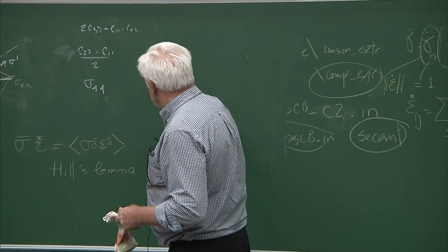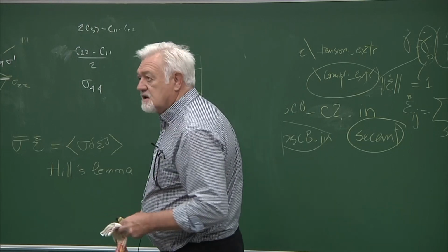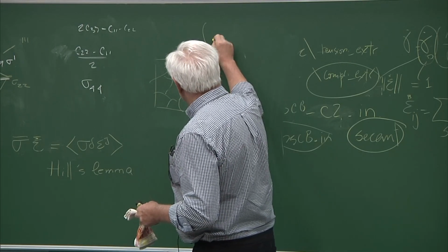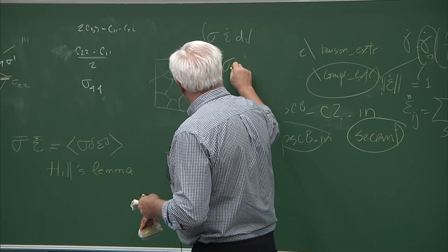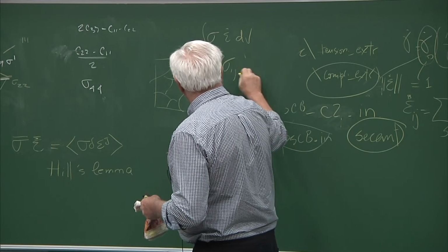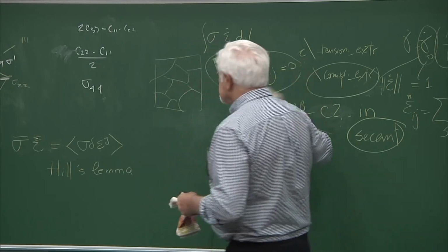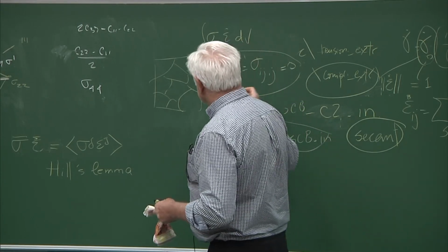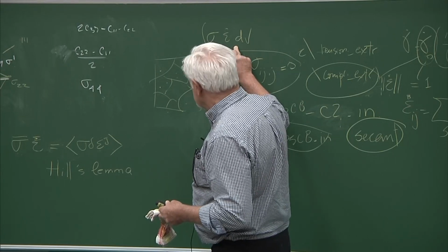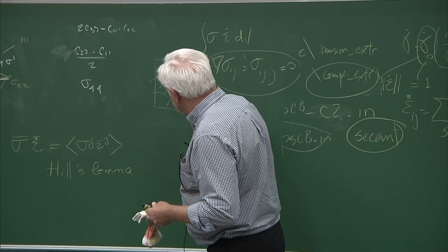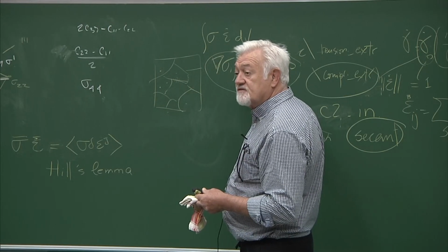for doing his demonstration, if you have a polycrystal, so you have your grains here, what Hill did, he calculated the integral of sigma epsilon dot differential volume, and he assumed equilibrium, the gradient of sigma ij, or sigma ij comma j, is equal to 0. This is the equilibrium of stress condition. Now, this condition he assumed is true everywhere, at every point in the material when he calculated this integral. So that means that when you go across boundaries, you have to assume that the stresses vary in such a way as to verify this.